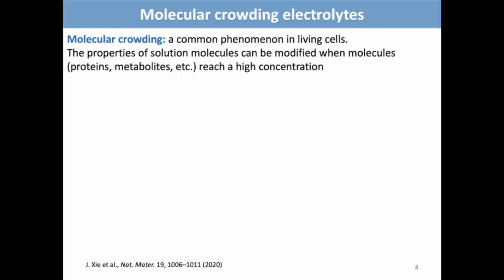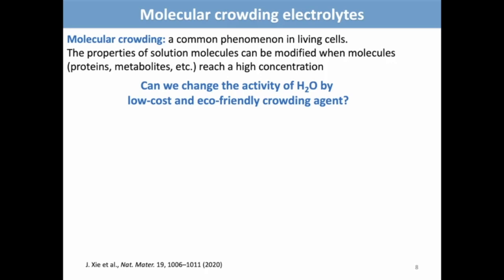So when we started thinking about this problem, we were thinking, how can we avoid using highly concentrated electrolyte but still stabilize water? We were inspired by a common phenomenon in living cells called molecular crowding. Molecular crowding essentially states that the activity of water can be significantly modified if we have large molecules such as proteins present at high concentrations in the solution. So changing water activity using a large amount of molecular crowding agents could change activity. We were thinking, could that be a path to reduce water decomposition using low cost and eco-friendly crowding agents?